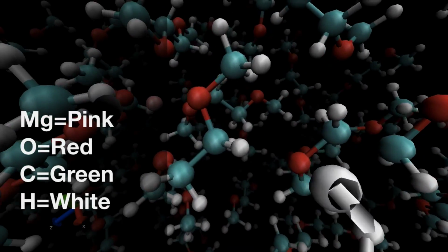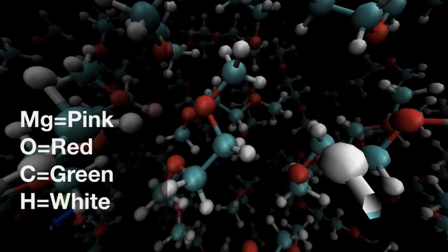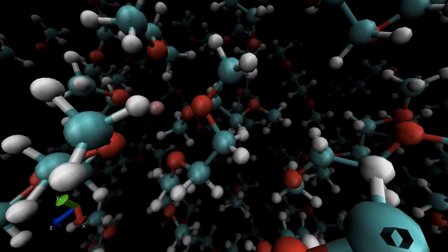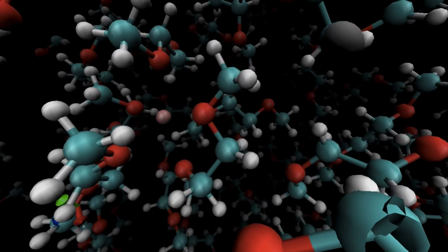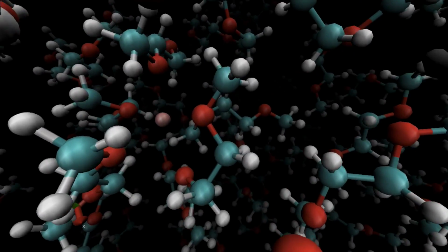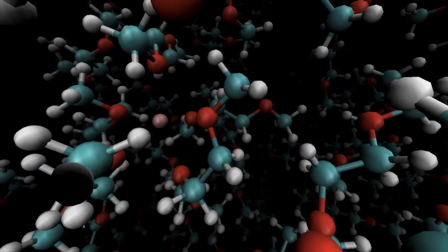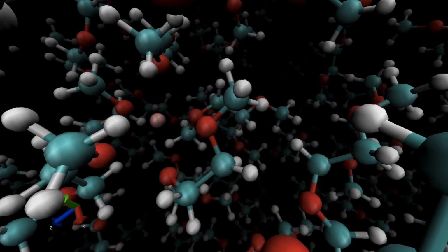After quantum chemical calculations and parameter fitting to get a force field that accurately describes the interactions of the salt and the solvent, I run an MD simulation of the electrolyte. In this simulation, there are 125 DME molecules and a single magnesium cation. By watching these interactions, we get an idea of the coordination of the particles in the electrolyte. We see that the magnesium is coordinated inside of 6 oxygen atoms.